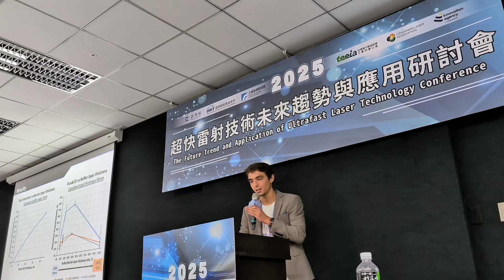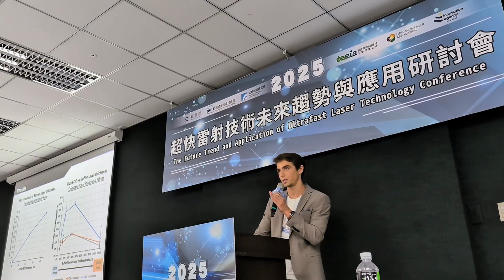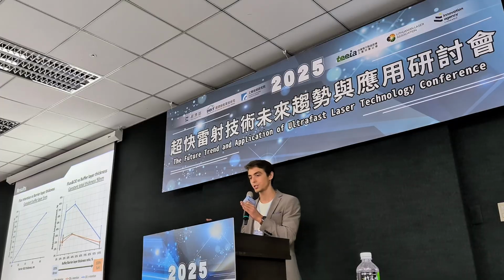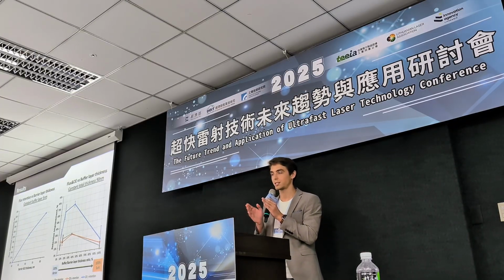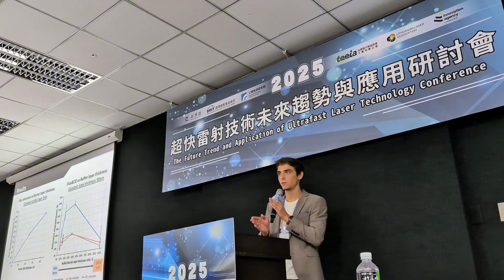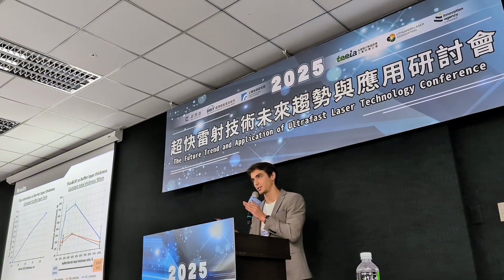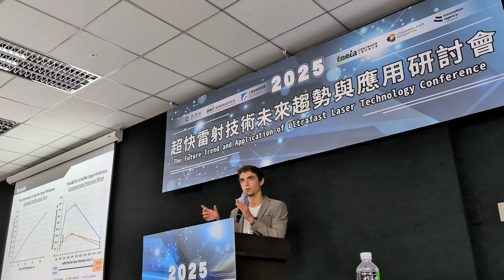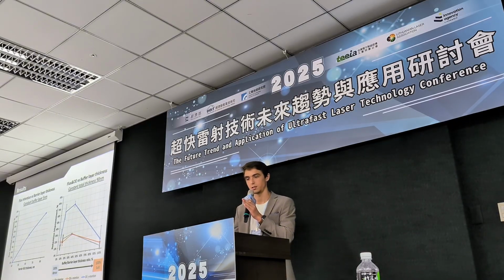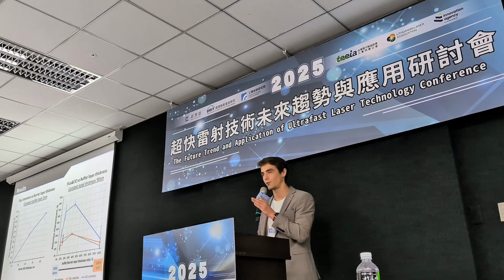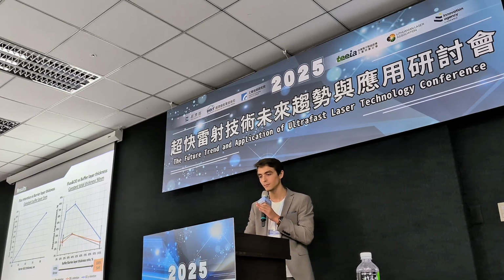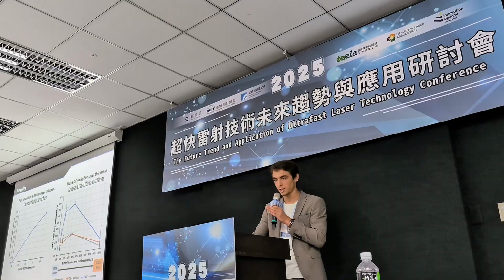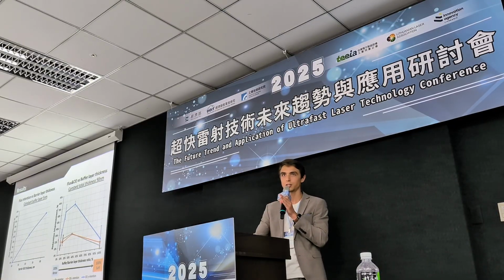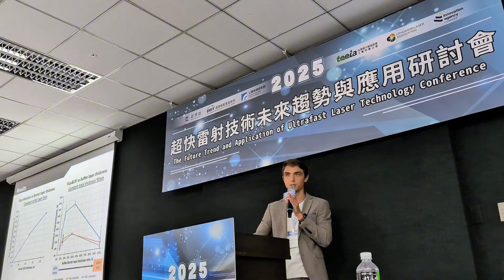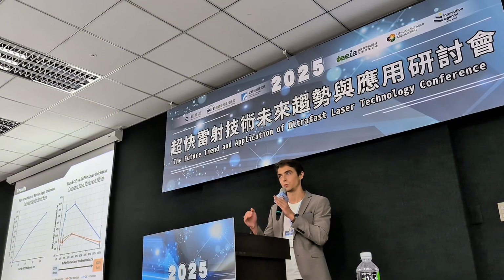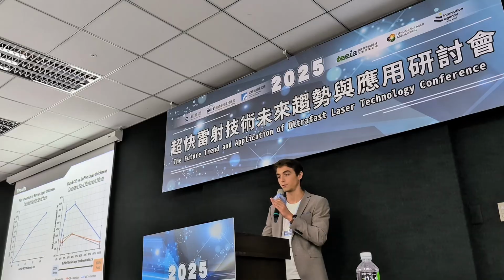And here is the result. We passivated many LEDs with different approaches and measured the light intensity before and after the environmental stress test. The stress test was conducted for 336 hours in a silicone oil, hydrogen sulfide environment with high humidity. The vertical axis shows how the degradation of optical properties was reduced, or how optical retention was improved after some steps of deposition.